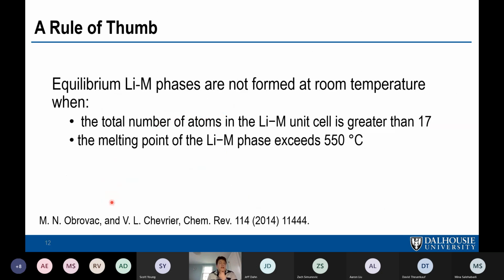And Vincent Chevrier and I looked over all the lithium metal phases that were formed at room temperature, and we basically found a rule of thumb, which was when the total number of atoms in a unit cell of an intermetallic compound with lithium is greater than 17, and if its melting point exceeds 550 degrees Celsius, you'll never see the phase at room temperature lithiation. It doesn't form. And so we looked at this and verified it was true for every lithium metal binary system.